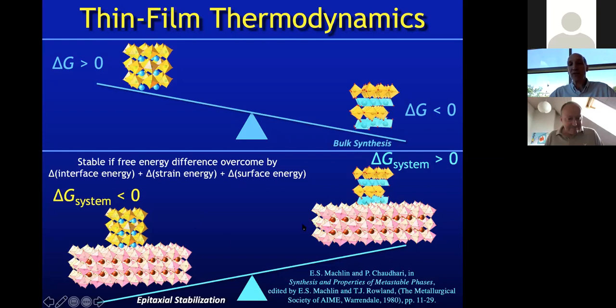an appropriate substrate, one that is not well lattice matched or structurally matched to what was the stable phase, okay? So you deliberately choose a substrate with the same kind of structure, the same mosaic, the same pattern as the material that you want to make. And then you rain down the atoms that you want to make.